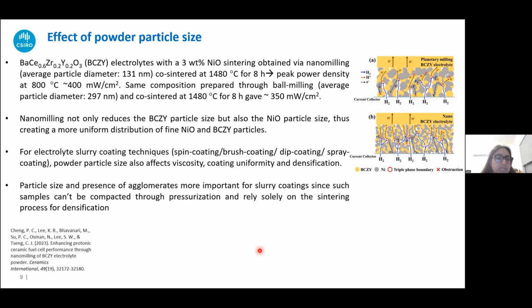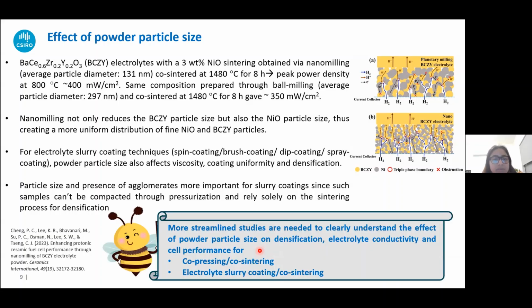So, especially for electrolyte slurry coating techniques, like spin coating, brush coating, dip coating, spray coating, or even tape casting, the powder and particle size is really important because it directly affects the viscosity, the coating uniformity and densification. In this regard as well, a lot of streamlined studies are needed to clearly understand the effect of the powder particle size on densification, whether it is for a co-pressing, co-sintering process like the dry process, or if you are first preparing your electrode or support material and then casting your electrolyte in a liquid slurry form.